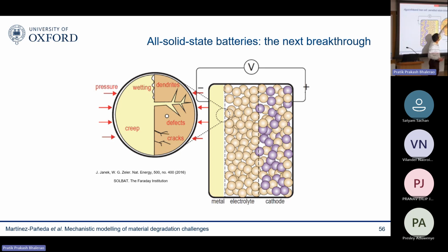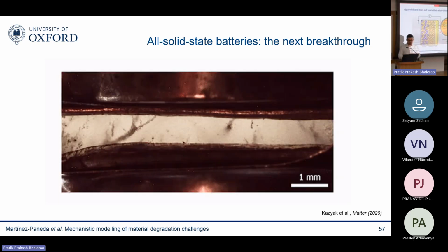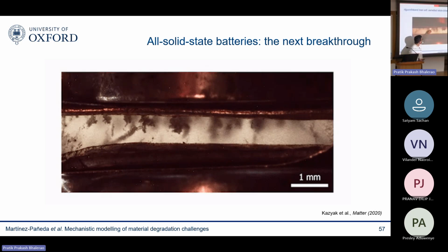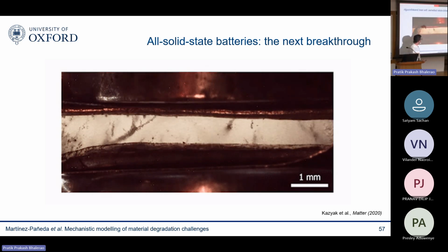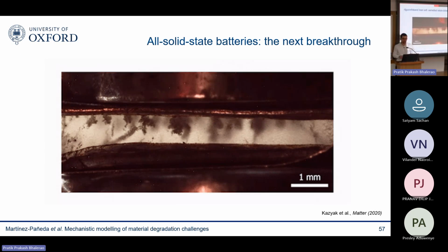And the main problem that we have is these dendrites, basically. These are kind of needle-like structures that are generated in the lithium metal and they grow all the way into reaching the cathode and therefore cause the short circuit of the battery. You can see an image of those dendrites being formed here. So here I'm rotating the battery. So this is the electrolyte. And you can see how those dendrites grow through the electrolyte until they reach the cathode, and then you get a short circuit of your battery.